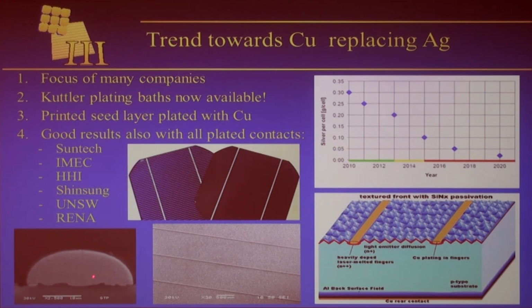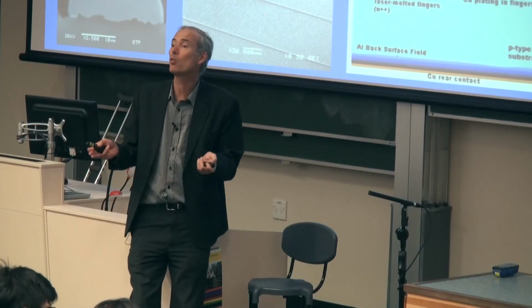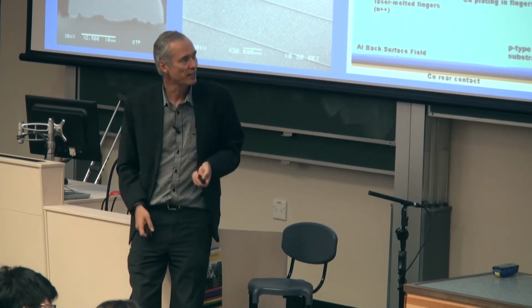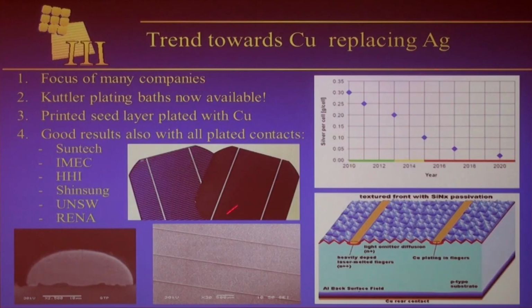And so here you see a couple of photos. This is a cross-section of a metal line. In this case, it's about 25 microns wide. In comparison, the screen-printed metal lines are typically 80 microns wide. So a big difference in how wide they are and therefore how much light they shade. And that's part of the reason why this looks so dark, except for the interconnect wires. This is very dark compared to this, where you can clearly see the screen-printed silver lines.